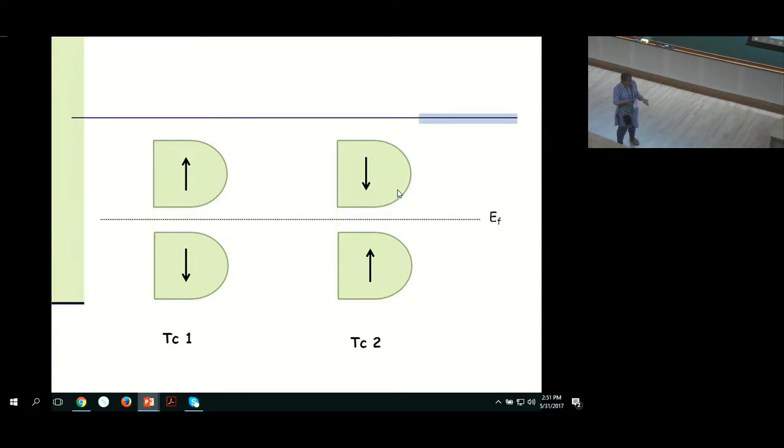The two factors which determine the effective exchange interaction strength are the hopping interaction strength, and the scale of JH, which determines the separation between these levels. Both end up aiding the superexchange interaction and therefore increasing the Néel temperature in these materials.